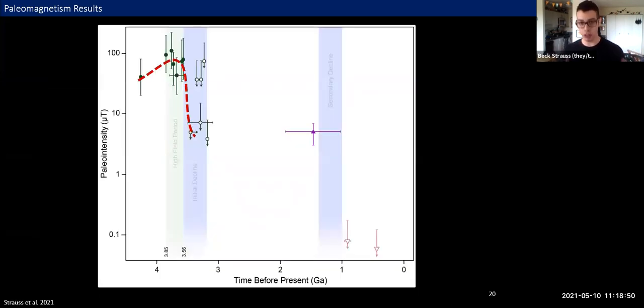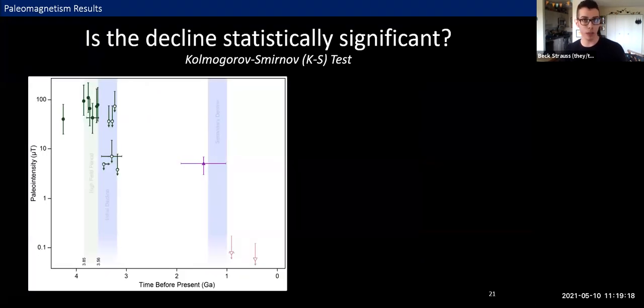So with all of that information and with our new argon-argon dates, we can add our 3 samples to this timeline that I was just showing you, essentially quadrupling the amount of data available right around 3.1 to 3.2 billion years ago. Our results are in very nice agreement with previous work. And that means this is essentially a replication study, which I think is very exciting because it lets us think back to that small number statistics issue I mentioned earlier. So we can ask the question then, is the decline after the high field period actually statistically significant?